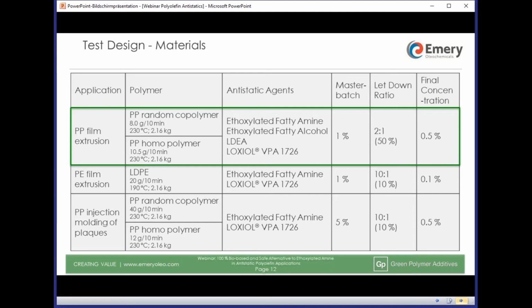All four antistatic agents were incorporated into these two polymers to form a master batch with 1% active and then a film with 0.5% active. A master batch with 1% of antistatic agent. You will rightly raise the question, why such a low concentration? It is because film extrusion was done using a single screw lab extruder, and we needed to make sure the antistatic agent would be properly dispersed in the film.